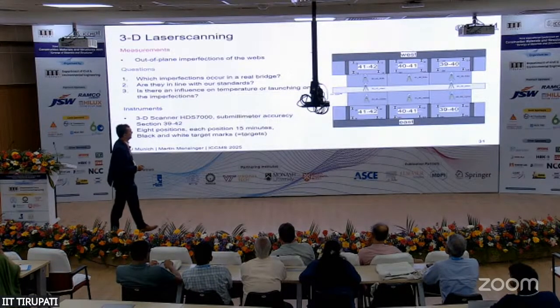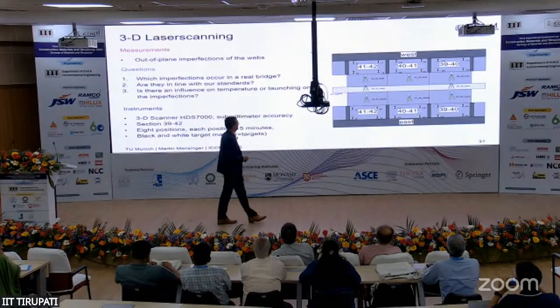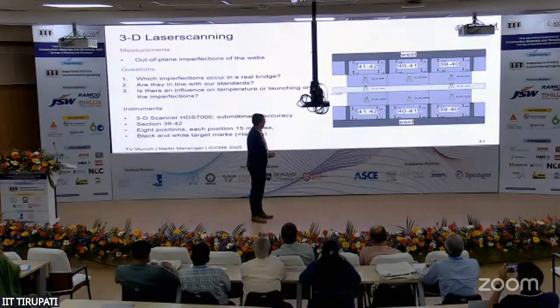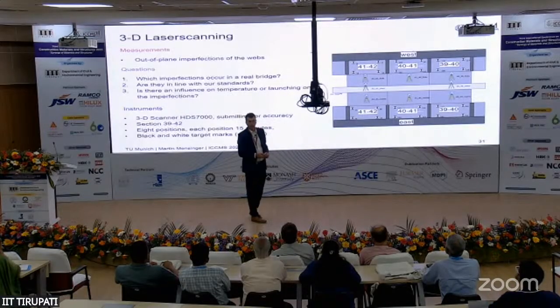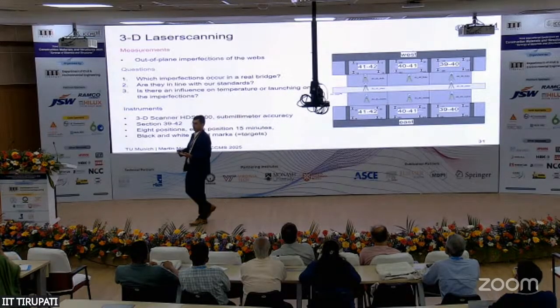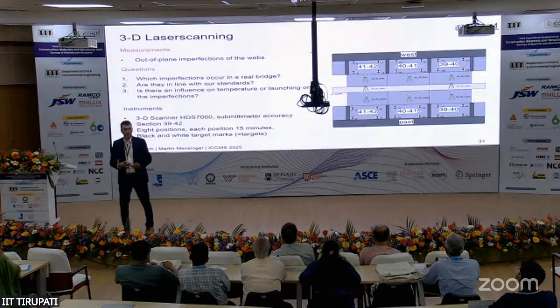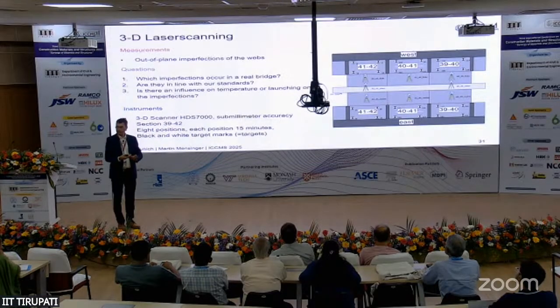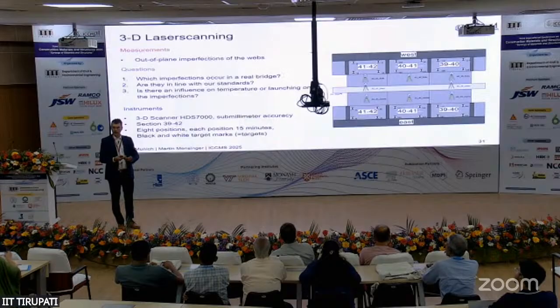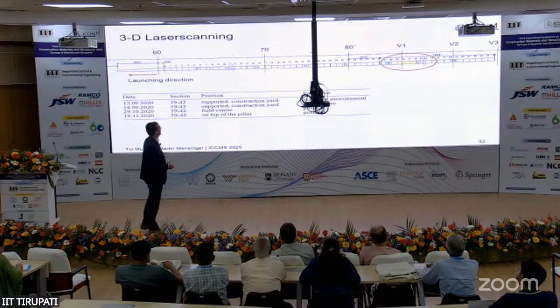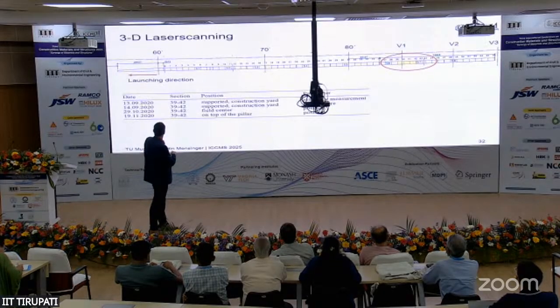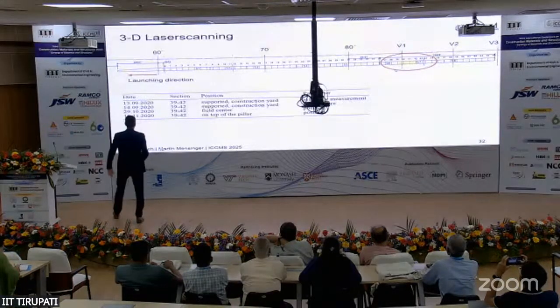And we performed some measurements with lasers in 3 segments of the bridge, and measured the deformation of the web and of those web panels during the erection of the bridge in different phases. So here is the bridge. This is the launching nose, and then we have the different segments of the bridge, and we were able to measure 3 panels, and we did several measurements.